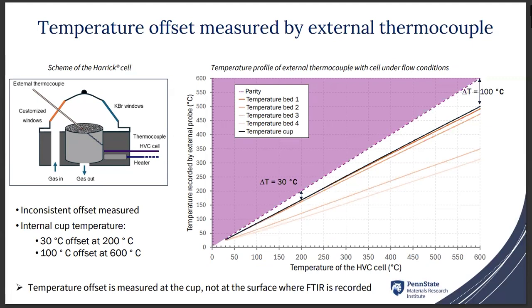So for that, we modified the cell so we can see that the thermocouple that gives the temperature is inside this metallic block where the heater is, and it's not where the sample is. So we customized the cell in order to put a thermocouple inside the catalytic bed or inside the powder bed, and we could record the temperature from the powder versus the temperature of the set point.